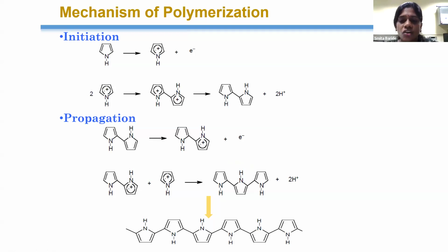Now if we see the structure of polypyrrole, all monomer units are combined to each other with 2,5 positioning, so an alpha-alpha bond. If this chain continuity is shifted to the other side, like 2,4 or 2,3 position, then it is called a defect in the polymer, and the chain continuity will be lost and the conductivity will drop off. So this is basically the mechanism of polypyrrole synthesis, and in a similar way the polyaniline synthesis also takes place. This is happening in the conducting polymer because of the presence of conjugated bonds.